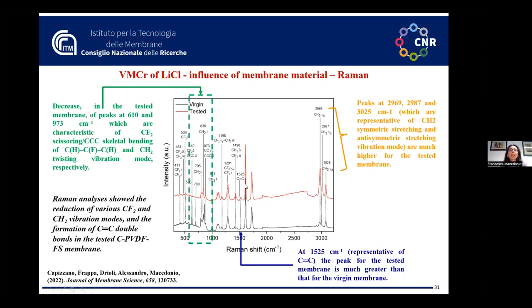And in fact, in the literature various works can be found proving that while PVDF membranes are stable when in contact with acid solutions, contact with strong basic solutions or with highly reactive compounds like lithium chloride causes a dehydrofluorination reaction, with expulsion of an HF group and the formation of this carbon-carbon bond.